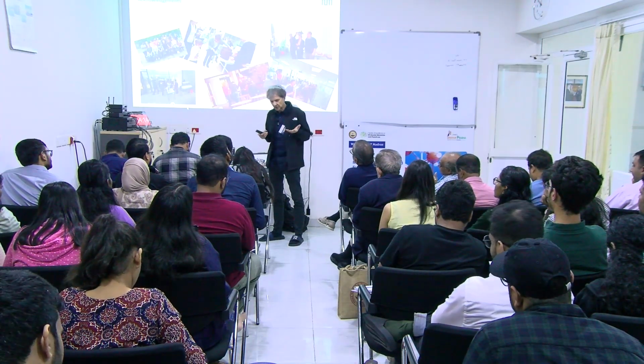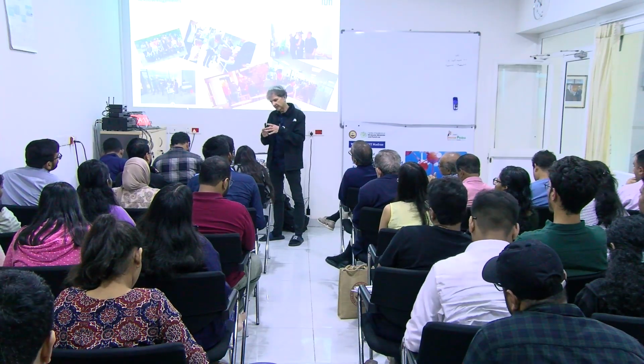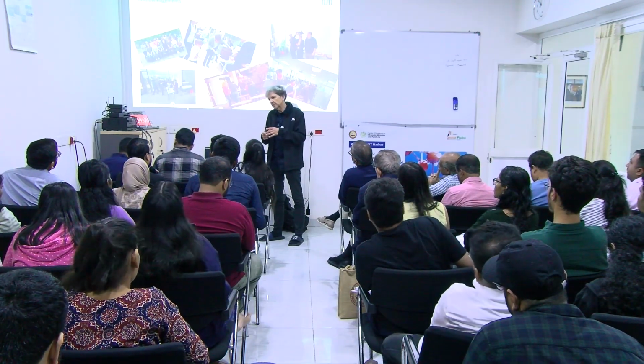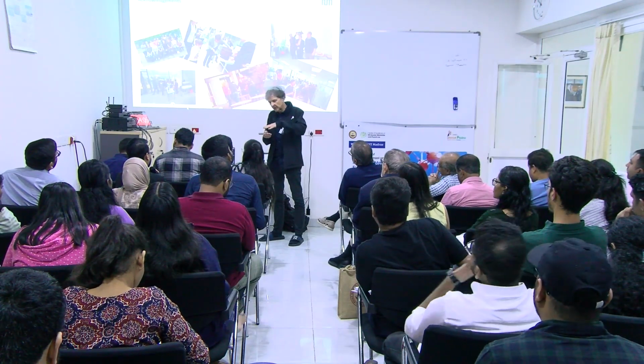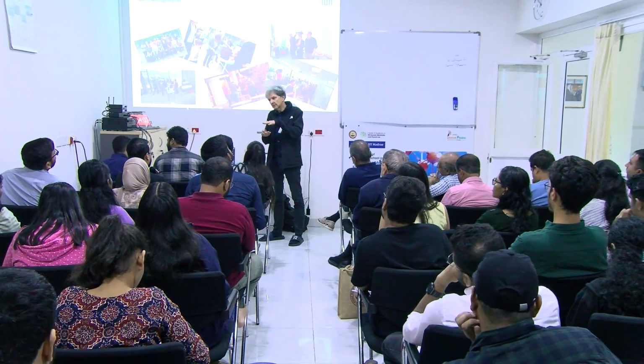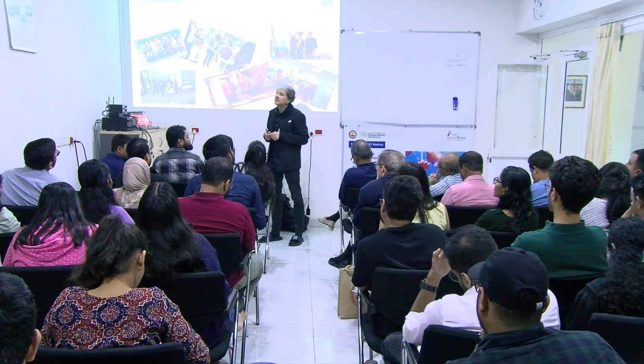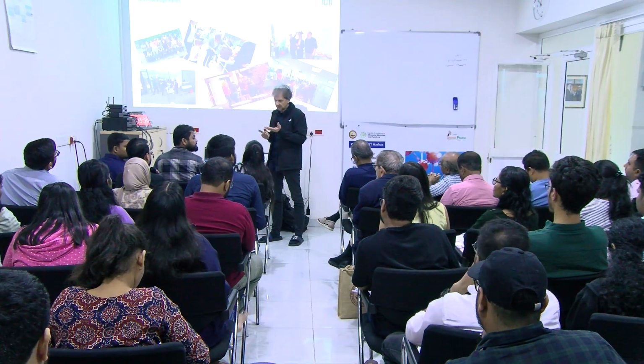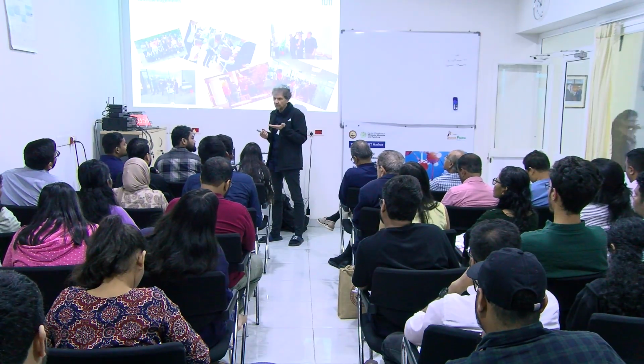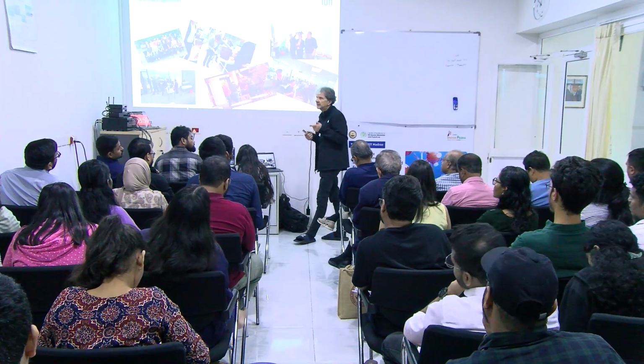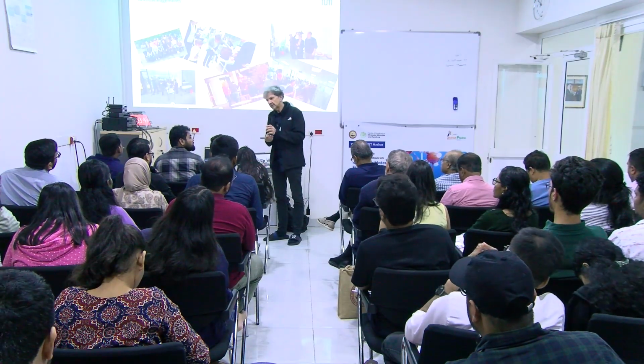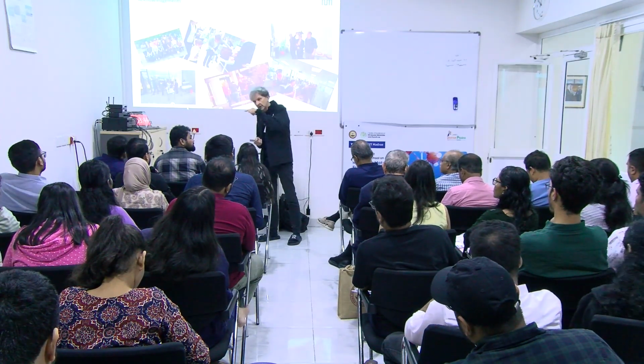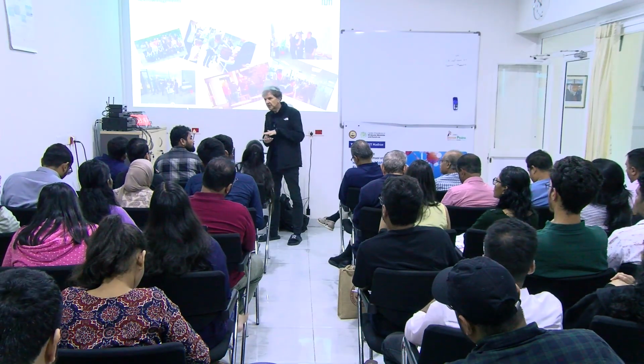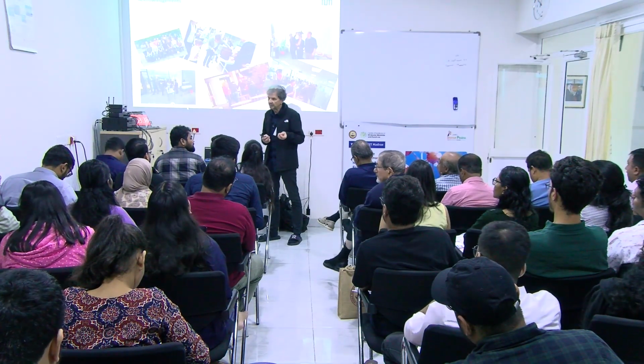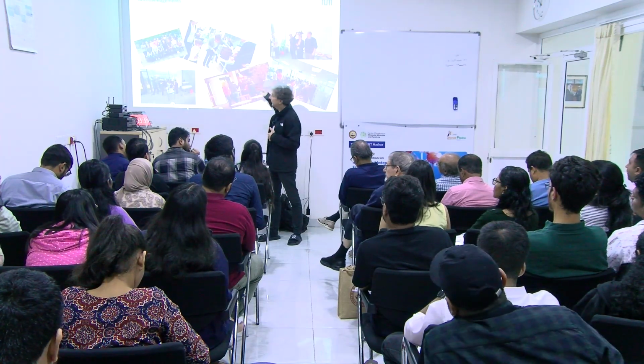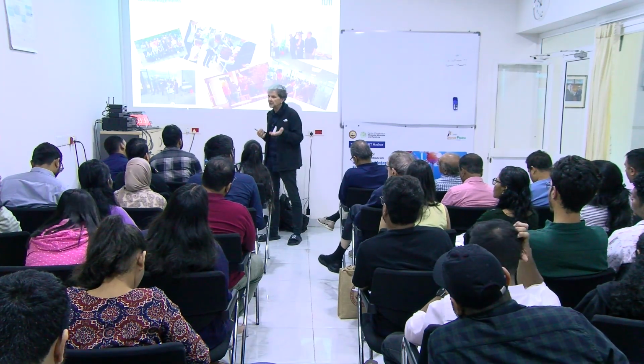I mean, we also showed on other substrates, if the area of interaction is large, you have a stable cluster. And for the smaller cluster where you have, let's say, a small contact zone, the mobility is much higher. And so it's strongly dependent on the support material. And also, if you have a weak interaction with the substrate, you have the preference of a Smoluchowski ripening. If you have a strong interaction with the substrate, you have Ostwald ripening. And so you can tune this ripening by the interaction of the cluster support.